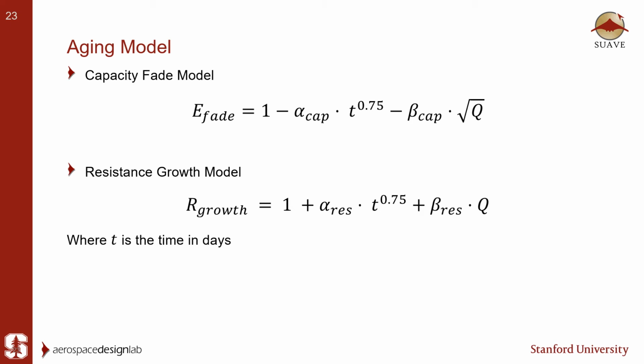Now, putting it all together, the superposition of the calendar and cycle aging thus provides a total aging function of the capacity fade as well as the resistance growth. One thing to note here is that the capacity fade has a square root relationship with Q, or the charge throughput, and the charge throughput is essentially how much current has passed through the individual cell. However, the resistance growth has a linear relationship with the charge throughput. Here, T is time in days.